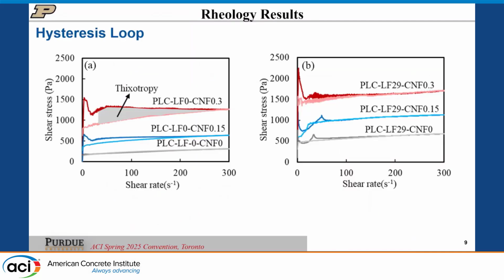Here are the results for the hysteresis loop. On the left-hand side is the PLC system with different CNF dosages, but no additional limestone filler. On the right-hand side, this is when we added 29% more limestone filler. What you see, at least on the left, is that as we're adding CNF, we are significantly gaining structuration - we're seeing an increase in the rate of thixotropy with the mixes.